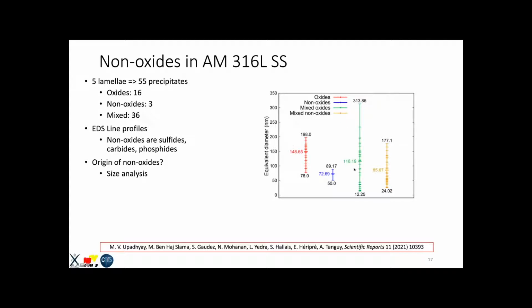As you can see here, this is a size chart, and all these dashes are all the precipitates that were existing in these 5 lamellae. We looked at the average values of these precipitates. This is only pure oxides, pure non-oxides, mixed oxides in mixed precipitates, and non-oxides in mixed precipitates. And you can see that consistently, the non-oxides are smaller than the oxides.